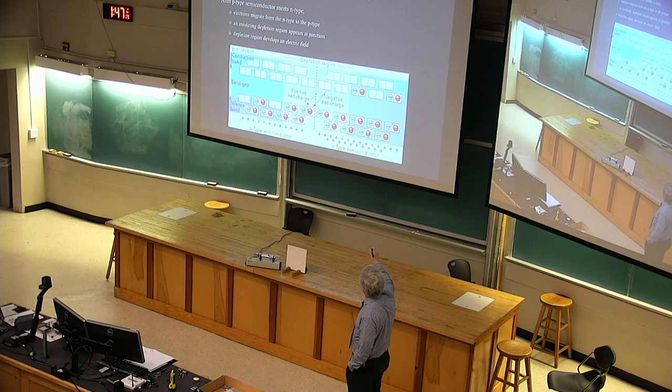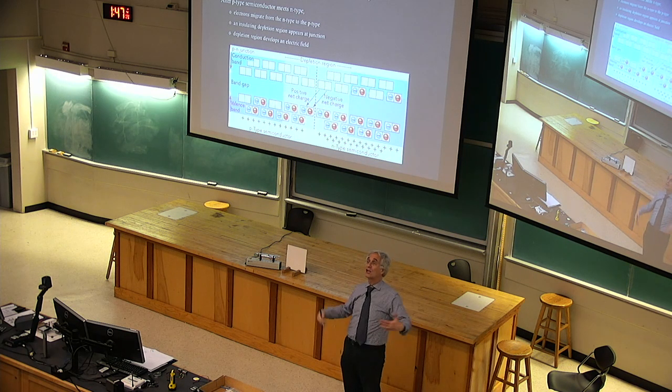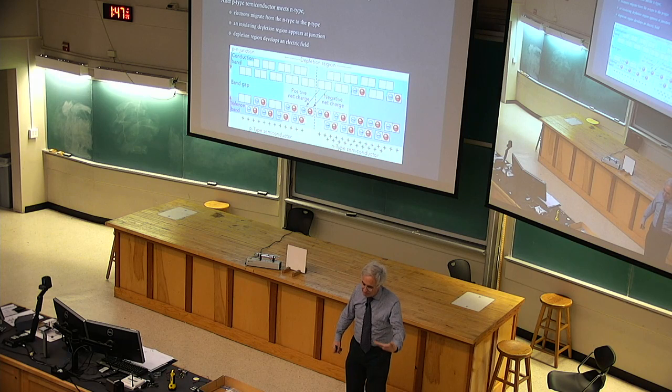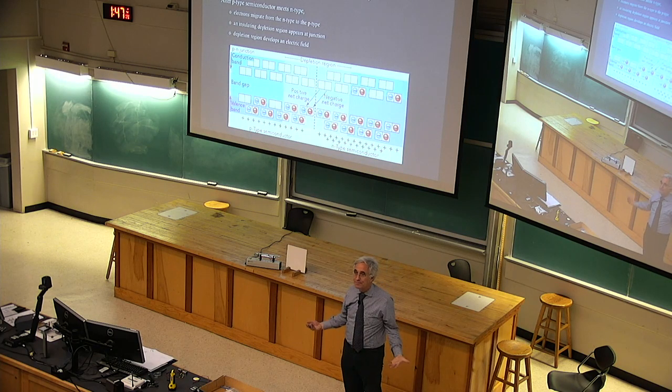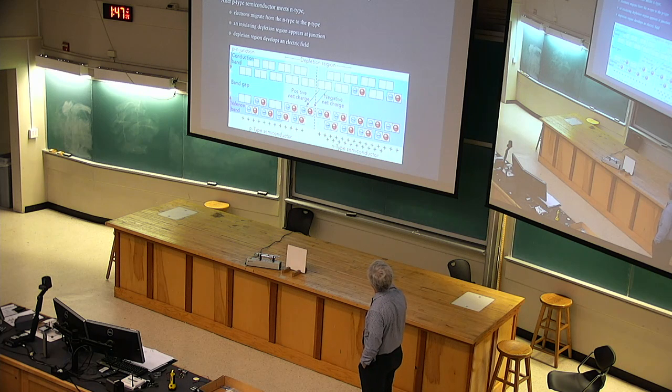The electrons near the junction do migrate across it, and they leave the conduction levels and enter the valence levels of the other side. So they leave the conduction levels of the N-type semiconductor and enter the valence levels of the P-type semiconductor, a process that releases energy. And they will continue to do this until they have built up a significant electric field in this middle part. As negative charges leave the right and end up on the left side, the left develops a net negative charge, and the right side a net positive charge, so there's an electric field there.